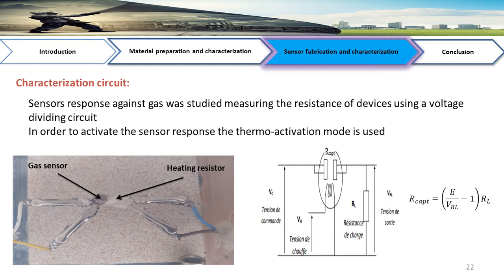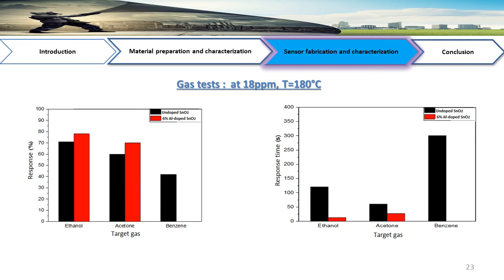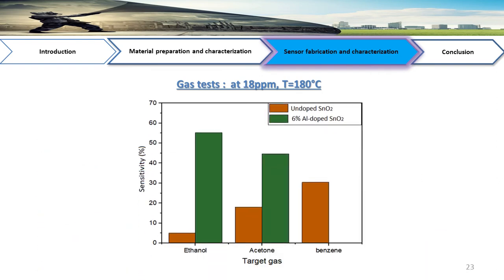The prepared sensors are based on microtubes of undoped tin oxide and tin oxide doped with 6% of aluminum. The following figure presents the characterization results of our sensors under ethanol, acetone, and benzene at 180 degrees. We observe that there is an improvement of the response and the response time by doping effect, and that the sensor based on tin oxide microtubes doped with 6% of aluminum has a high sensitivity to ethanol and acetone compared to the other sensor, and also has a low sensitivity to benzene.